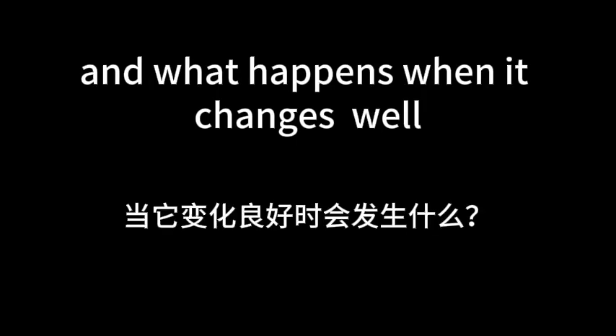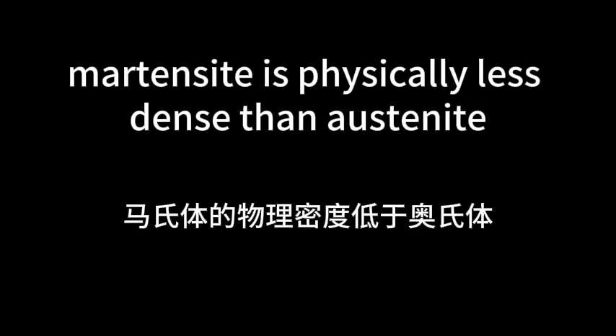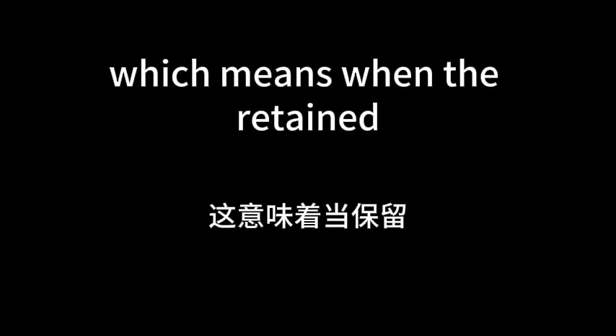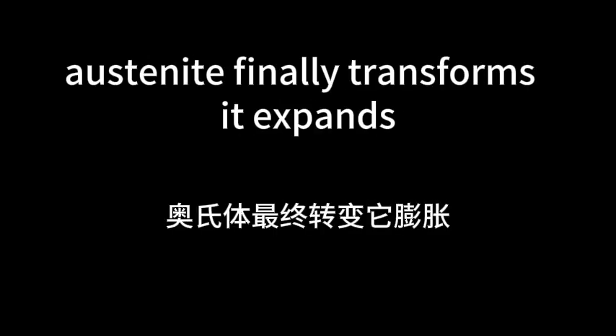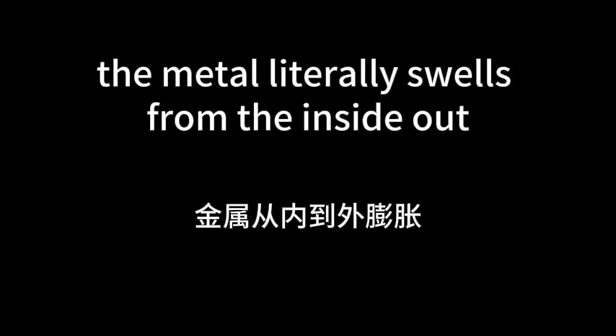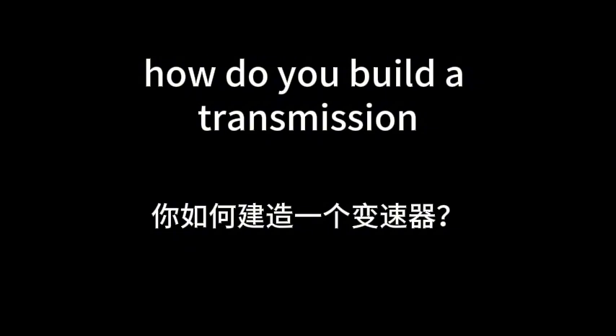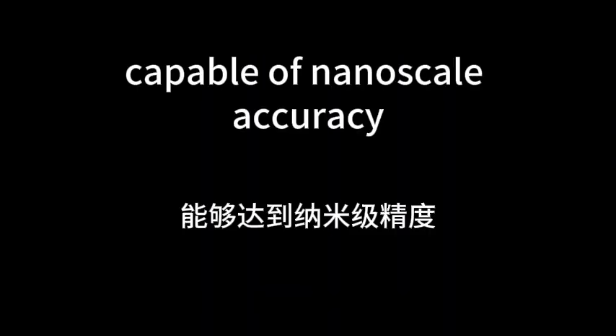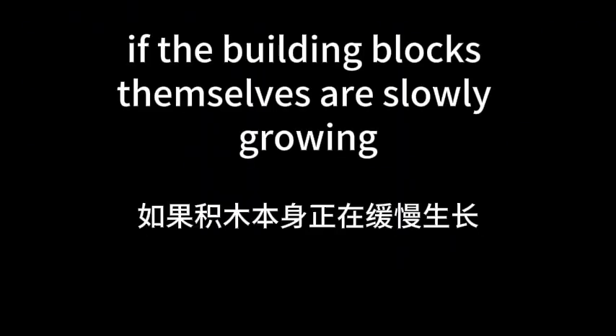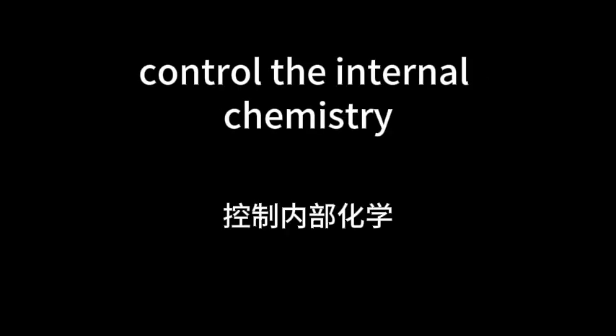And what happens when it changes? Well, martensite is physically less dense than austenite, which means when the retained austenite finally transforms, it expands. The metal expands? The metal literally swells from the inside out. How do you build a transmission capable of nanoscale accuracy if the building blocks themselves are slowly growing? You have to aggressively control the internal chemistry.